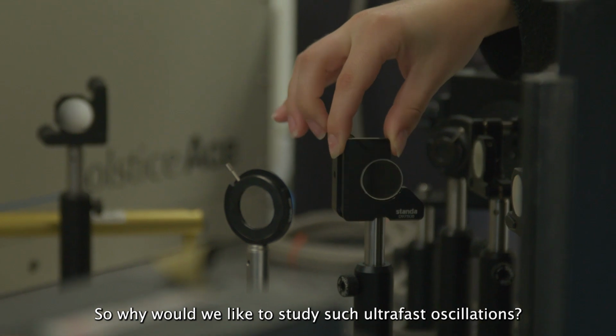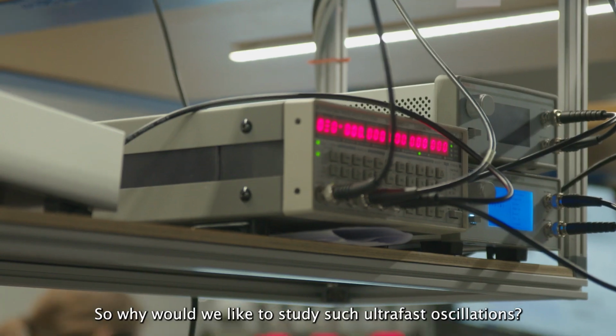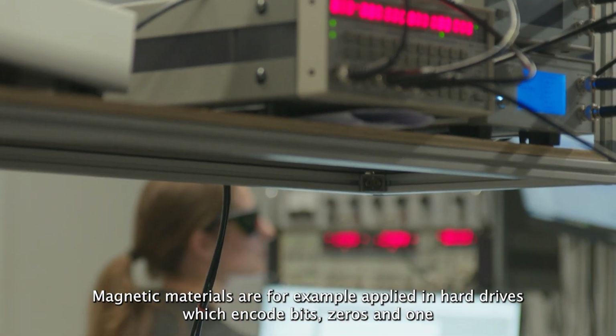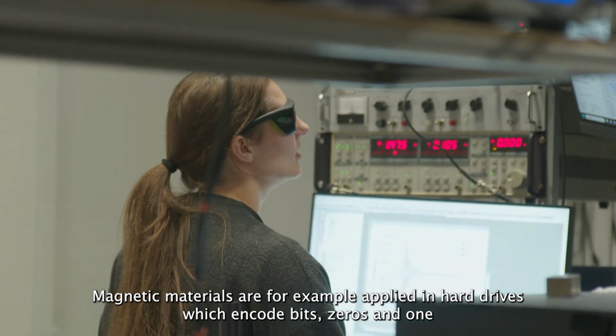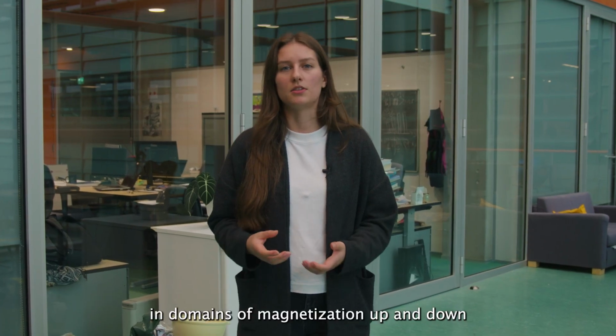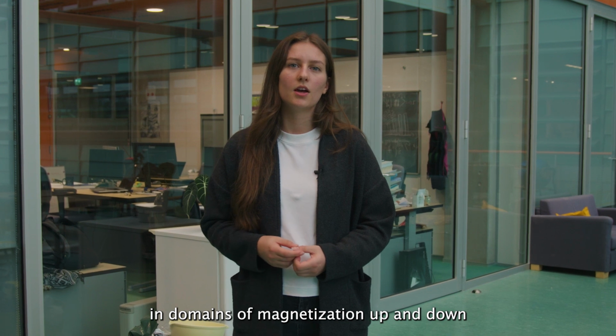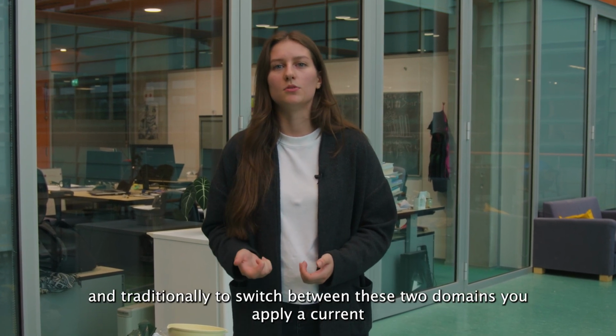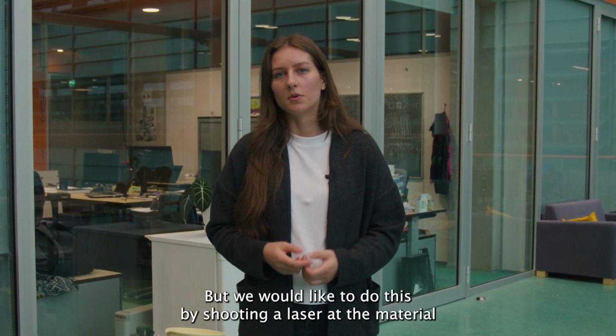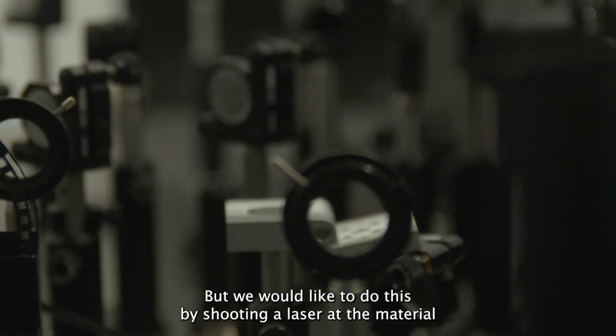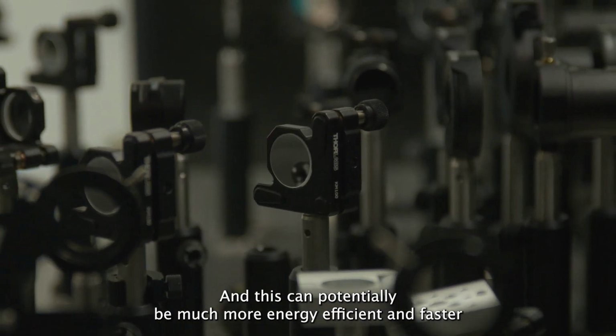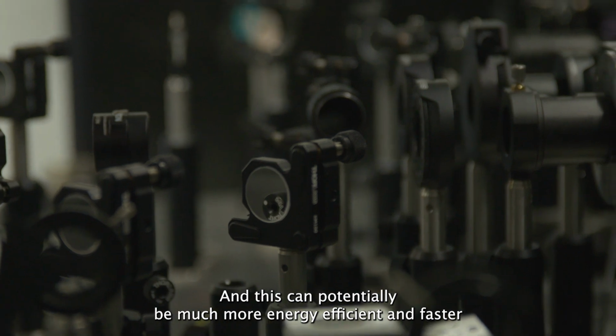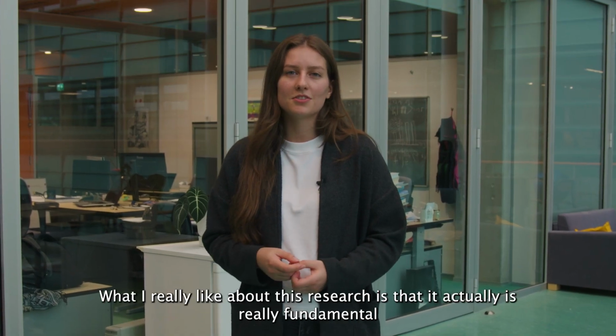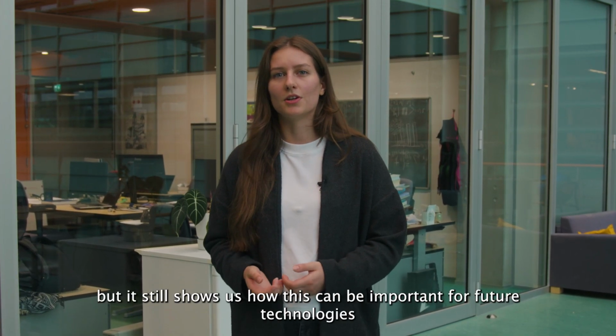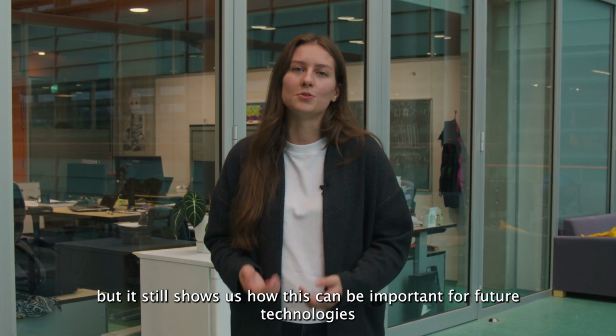But why would we like to study such ultra-fast oscillations? Well, magnetic materials are, for example, applied in hard drives, which encode bits, zeros and ones, in domains of magnetization up and down. Traditionally, to switch between these two domains, you apply a current. But we would like to do this by shooting a laser at the material, and this can potentially be much more energy efficient and faster. What I really like about this research is that it is really fundamental, but it still shows us how this can be important for future technologies.